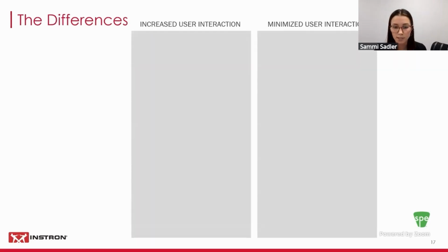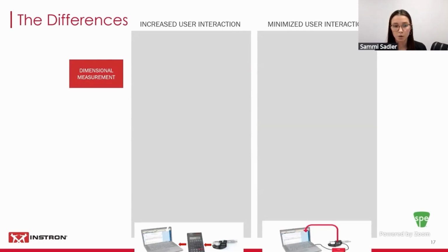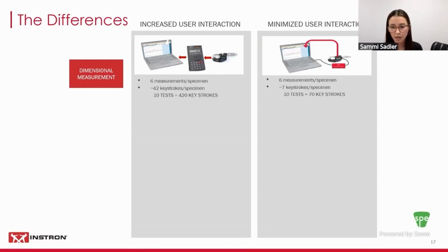ISO 527 requires the specimen to be measured at 3 different points along its width and thickness, and then after that, they must be averaged. Using a manual micrometer and calculator compared to an integrated micrometer, the keystrokes were reduced significantly when the micrometer was integrated directly into the software. So this reduced the keystrokes from 420 all the way down to 70. Just by adding a micrometer integrated into your software, you will reduce your test time significantly.